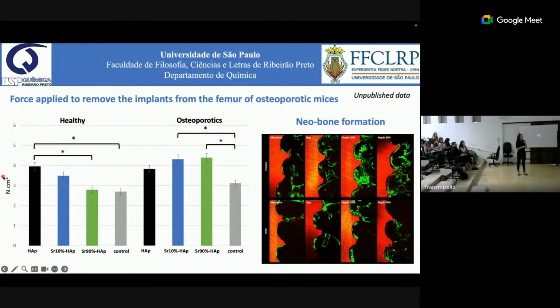But if you see, even in the healthy mice, the performance of the implants under the reverse torque assay was better. Also, the new bone formation that we show here by this confocal image, the green area corresponds to the new bone formation area. Here up, we show the surface of the titanium implants implanted in the healthy animals, and below, in the osteoporotic model, we see that increasing the amount of strontium, we increased the new bone formation. Obviously, in the osteoporotic mice, the bone formation was slower, but we see here that the presence of strontium was important to induce new bone formation.